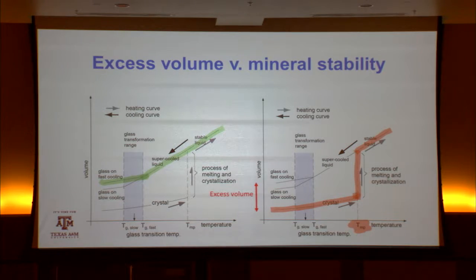On the other hand, if the silica-based sand that you're using has a high free energy because of rapid cooling, for example, and is amorphous in nature, then the probability for that to react in the high pH environment, pH about 13 or so, where silica is quite soluble, is high. So that's a reactive material. And it's reactive based on this principle, that the crystalline material cools slowly, it forms the bonds that are needed to lower its free energy. The amorphous material, which is cooled rapidly, is not as well organized. It has incomplete bonds. It has a higher free energy. Nature wants to reduce the free energy, and at that high pH environment, it will be soluble and react to lower its free energy.